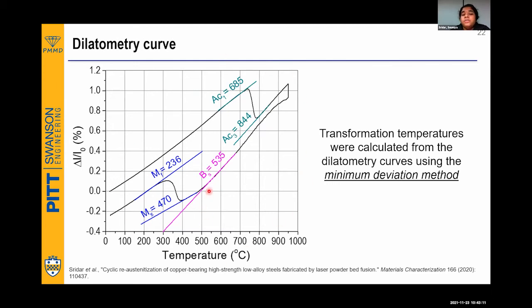In this case, actually, we couldn't record one temperature, which is called the BF temperature. That is the bainite finish temperature. Unfortunately, for many steels, the bainite finish temperature mostly coincides with the MS temperature. So that's the reason we were not able to figure out the BF, but we could get only the BS temperature, because as you can see, the length change is also not so obvious in this case.